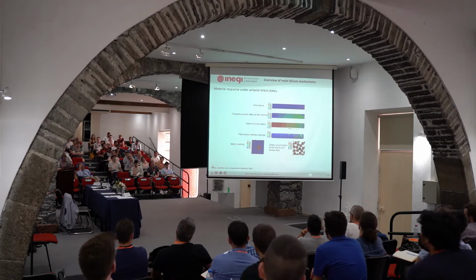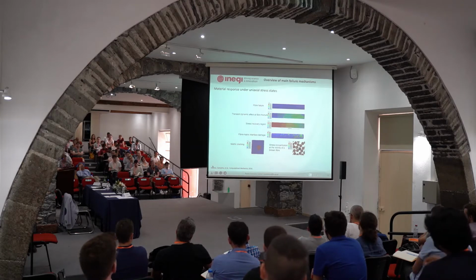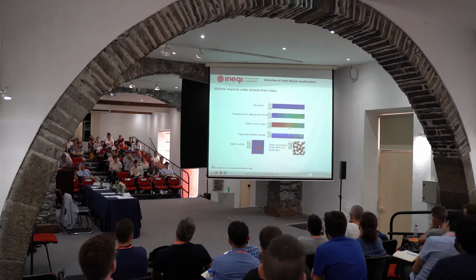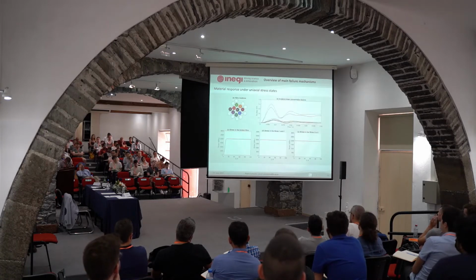of the fiber, and you can see that then there's a stress concentration at the fibers that are located in the vicinity of the broken fiber. Okay, so we can further look into these effects with another simulation that we have performed, where you can see here, this is our microstructure. So BF means broken fiber, and here you have fibers from 1 to 8, okay? Different positions, random positions. So here, this is time, and this is the stress concentration factor.